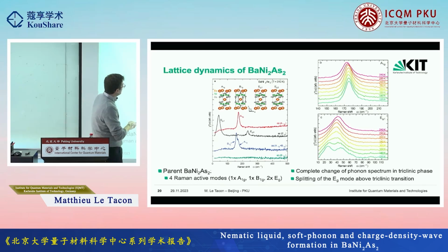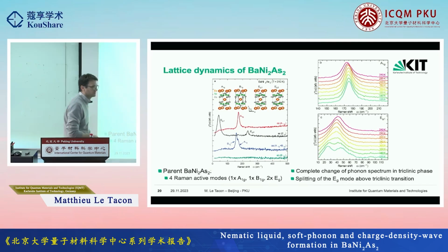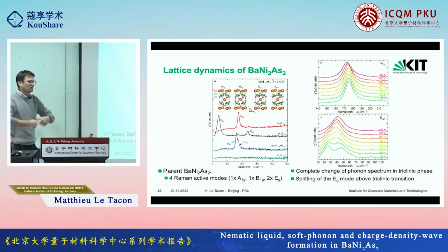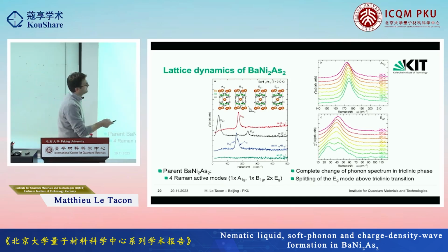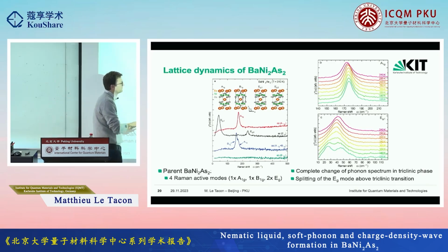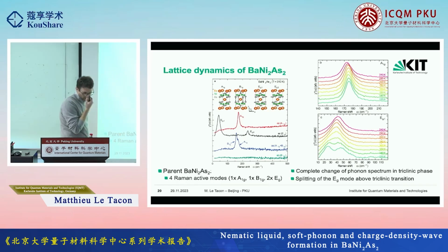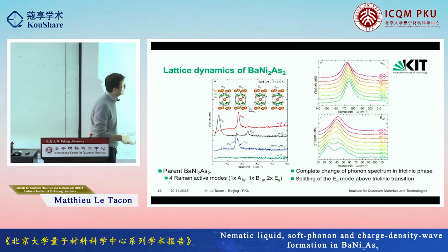Okay. Now, what happens above the triclinic phase then is more interesting. So I look at this A1g mode, and you see that it's nicely sharpened and hardens as any good phonon should do. The lattice contracts, the vibration of the lattice gets stiffer, and the anharmonic effect decays, so the phonon lifetime, which is inversely proportional to the width of the phonon, decays. So the A1g mode behaves absolutely as it should, and this is great. Now the Eg mode, this doubly degenerate mode, is a different story.